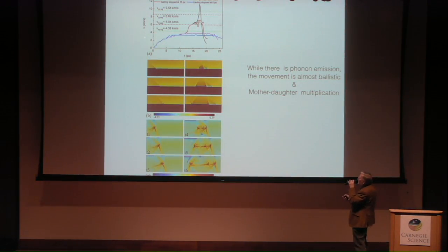So here is, over time, the speeds. 4.38 kilometers per second is one speed of sound. There's another speed of sound. And the top one here, 9.58, is the fastest speed of sound in that particular material, as we simulate that. And here is the speed as it is seen by the kink.